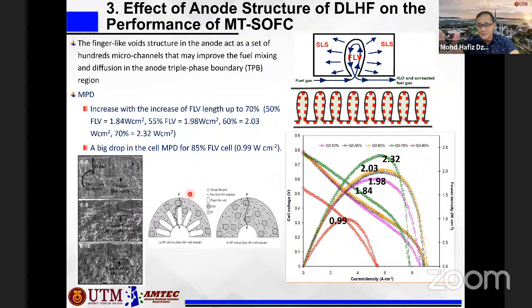Why we need to have a finger-like structure is because when we flow the fuel inside the anode, just imagine there is no finger-like structure, only a sponge-like structure. We don't apply too high a pressure for the feed to travel inside the anode; we apply just the right pressure. So with the applied pressure, the fuel probably cannot reach the inside area of the anode. It can only reach the outer layer, probably up to a few microns from the surface. So when you have a very small area for the reaction to take place, much of the anode area will not be utilized, and therefore it cannot produce more electrons.